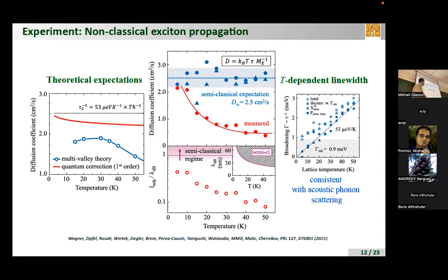Maybe I do not fully understand your question. What do you mean by drift? You mean the drift caused by exciton-exciton interaction? Yeah, just the ballistic propagation of this cloud. It's a good point, but I believe that experimentalists check very carefully that they work here at very low excitation densities, typically less than 1 exciton per optical pulse, and they do not see any significant change, more than 5% in the diffusion coefficient in this temperature range, when changing the power within several times.